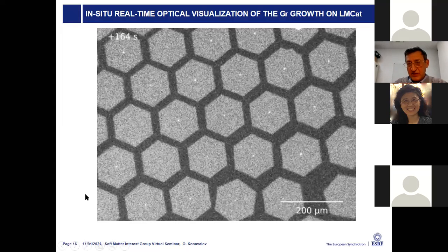and then to produce large-area graphene flakes. So here you see the scale: this is a 0.2 millimeter bar, and this is only one type of growth where crystals are reasonably small, but we can grow one single flake of graphene more than 2 millimeters. And you see that this whole process, what you saw on the screen, is happening within 3 minutes.